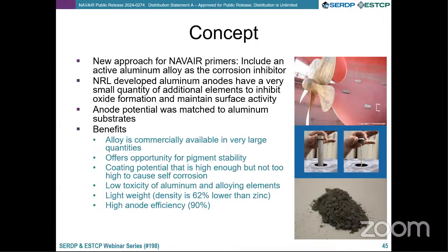And so because the electrochemistry of the structural aluminum on aircraft, the 7,000 series, is not all that dissimilar to the Navy ships, these anodes were well matched in terms of open circuit potential and anode efficiency to protect our Navy aircraft. Likewise, they're suited for aircraft use as opposed to zinc or some of the other alloys, because aluminum anodes are lightweight, and we have the ability to tune their activity, and I'll explain this in a minute.